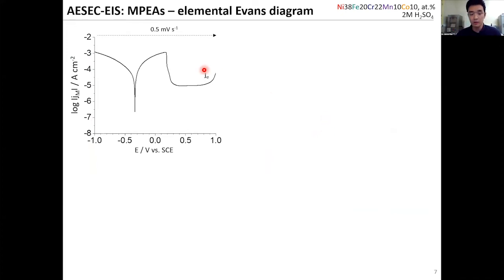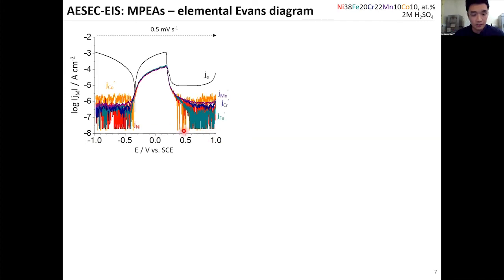So before starting on the AESEC impedance for the multi-principal element alloys, I'm going to start with a little bit of polarization curve, a more conventional way of electrochemistry. What you are seeing here is the conventional polarization curve with the current density as a function of scanned potential. The AESEC technique can give us more information, elemental results. I forgot to mention, this is a nickel, iron, chromium, manganese, cobalt alloy in 2 molar sulfuric acid.